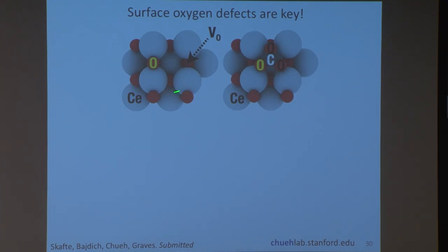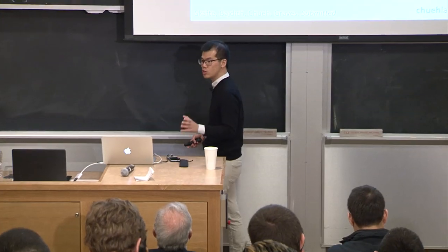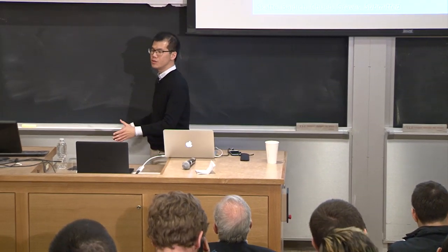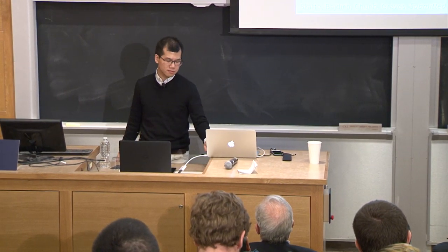So you see there's a missing oxygen right there. And that's what's allowing the CO3 2- carbonate to form in a very stable manner. And this is the key design rule, is you have to trap the carbon in the form of an oxidized carbon. You don't want it to trap as carbon, then that's how you get the poor selectivity.